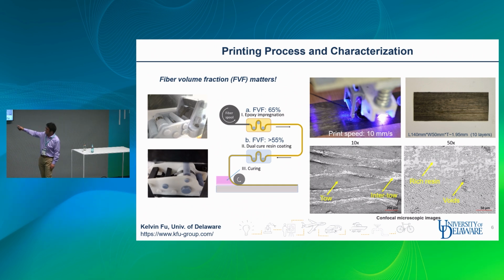So here we show that that is our epoxy design, the epoxy reservoir. So we can achieve fiber volume fraction up to 65%. And with the dual cure resin coating, we can still achieve over 55%. So this can reach aerospace grade high performance composite fiber volume fraction level.